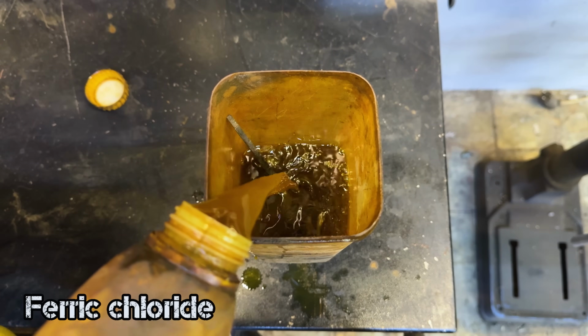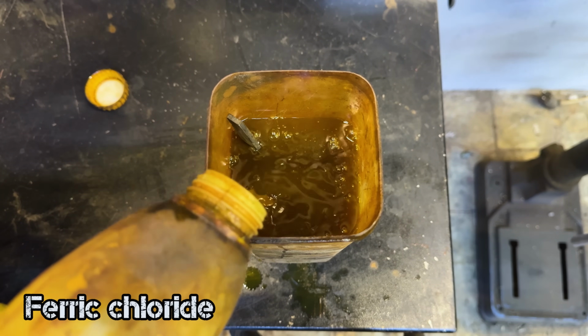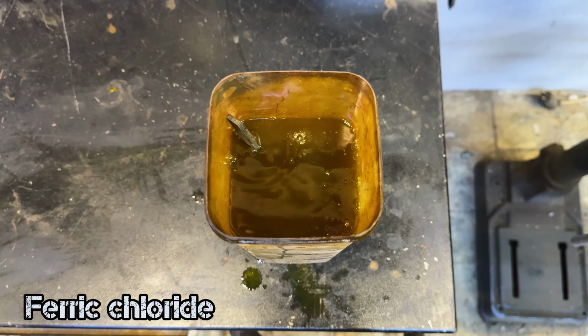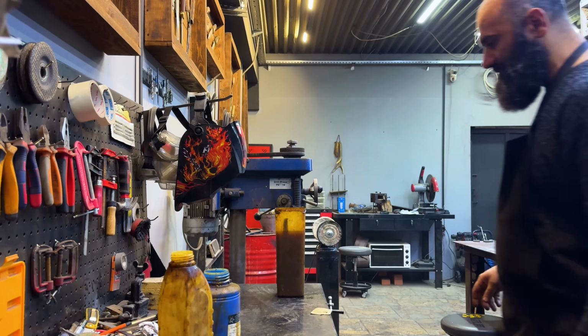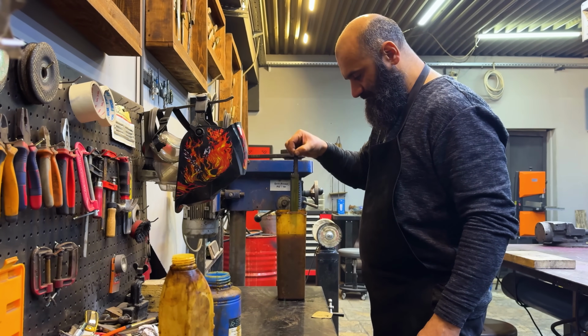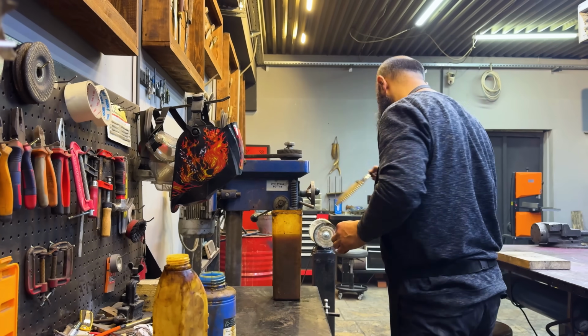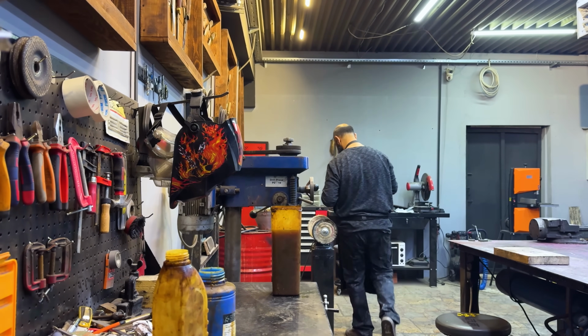Now for the Damascus pattern reveal. We're dipping the blade in ferric chloride, a strong etchant. The different steels in the billet react differently to the acid. The high nickel layers resist the etch and stay bright, while the high carbon layers etch dark. This is how you make the pattern pop.